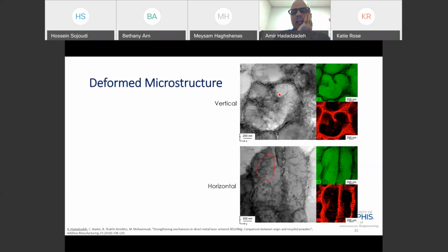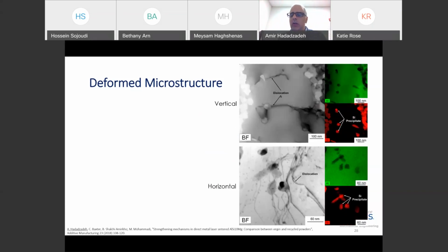So these dislocations, as you see, for example, in this case, in here, we have a higher density, and we have measured that, a higher density of dislocations, and these dislocations, again, are hindered by the eutectic silicon balls. For example, in this case, we have higher density of dislocations close to the eutectic wall. So those eutectic walls are acting as barriers against dislocation motion. So they are playing a role in terms of a strengthening mechanism.